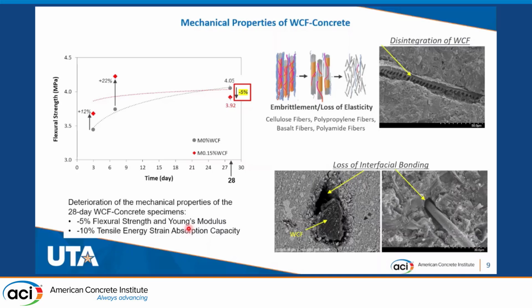Upon further examination, it appears that these cellulose fibers are quite sensitive, especially in the highly alkaline environment of concrete. The cellulose fibers tend to suffer disintegration, which is also known as the embrittlement of fibers, which leads to a loss of elasticity of the fiber surface and the formation of cavities. As shown in the SEM picture in the upper corner of the slide, this process results in a loss of interfacial bonding between the fiber and the matrix and explains the reduced tensile load bearing capacity of the composites, which we observed from the mechanical properties.